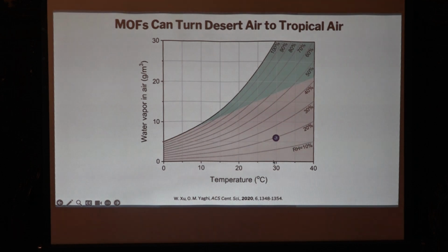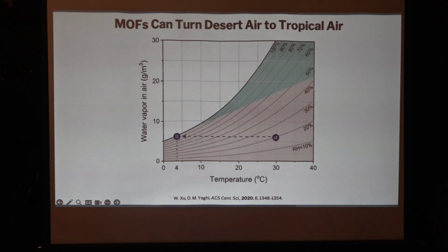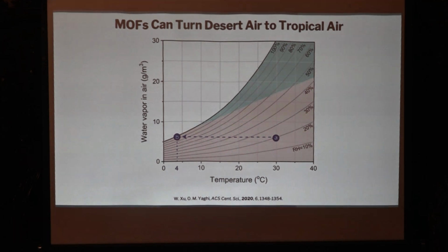And I'm at 30 degrees Celsius and 20% relative humidity. For me to take water out of that air, I have to cool down the air to 4 degrees Celsius. I can get the water out, but that's not very practical. Now, if I have a MOF that's programmed to take water out of arid air and compact it in the pore, and I put it in a closed box and expose it to the sunlight, water will come out of the pores and condense on the walls.